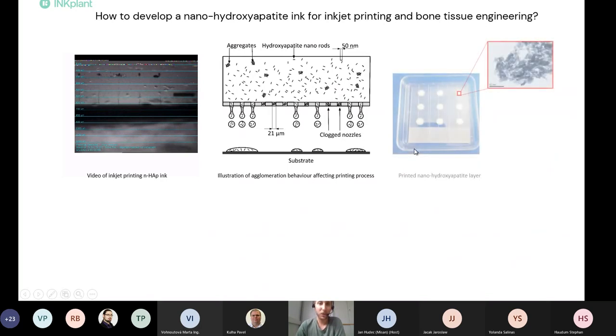We tried first printing tests and tried to formulate first formulations. We checked the jetting behavior, deposition of material, and tried to print thin layers, as we want to use this as a bioactive coating.